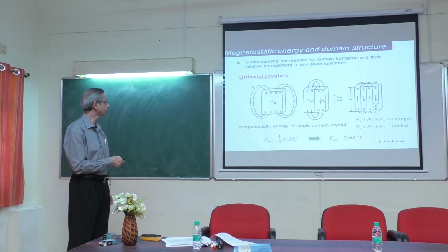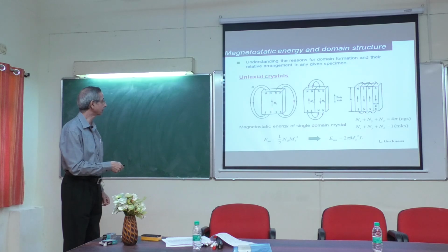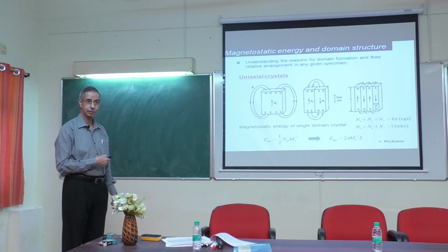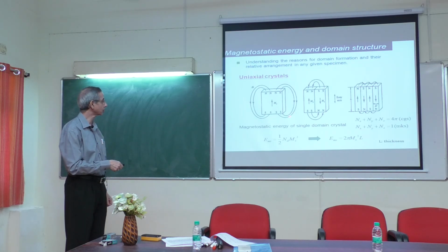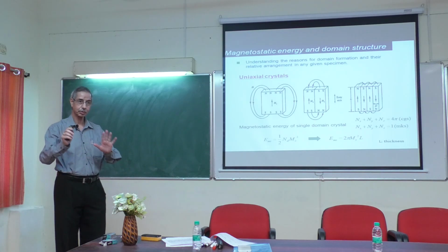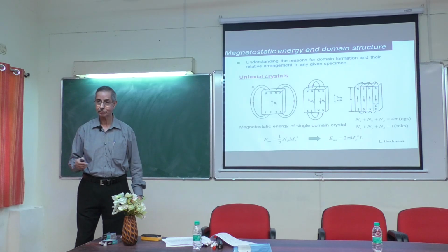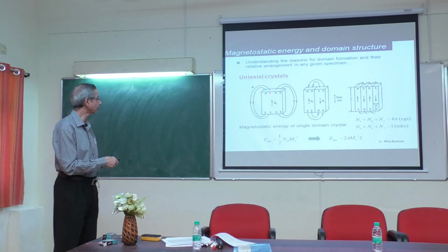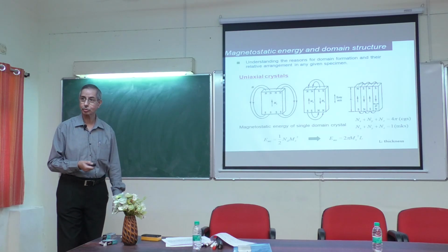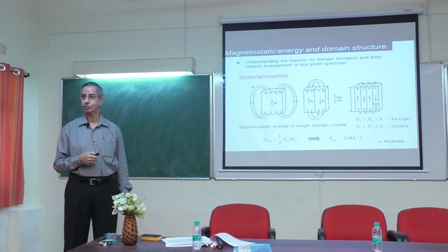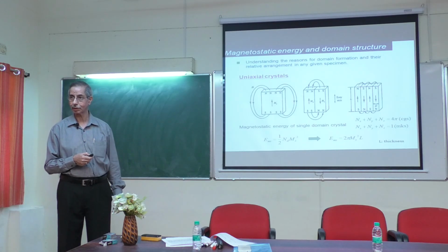But then the problem is this, because now the magnetization vectors are pointing like this, which is the domain resultant magnetization. So then there are these south poles, north poles induced here. Okay, so now there is this possibility of these field lines going like that, even in the absence of any external magnetic field. Because of these lines, they give rise to a large magnetostatic energy. It's a huge magnetostatic energy.